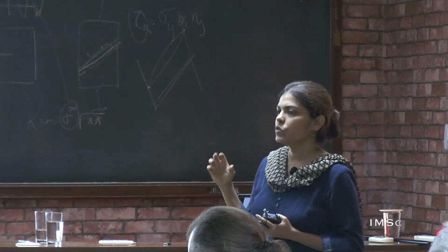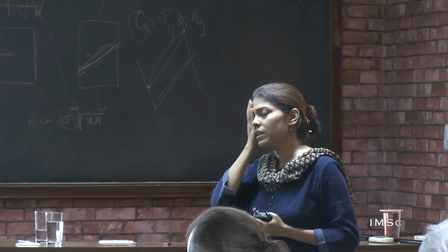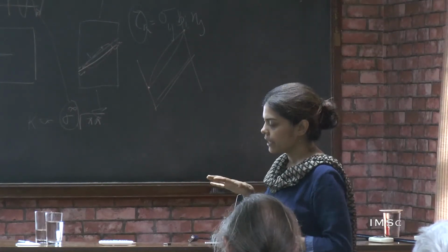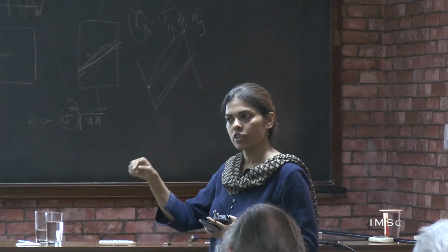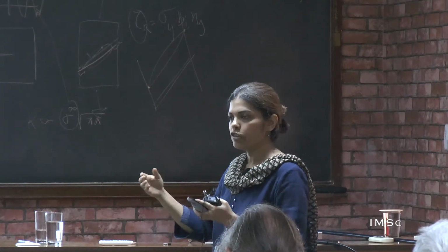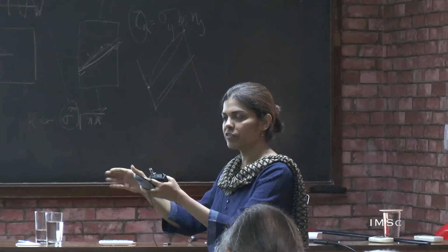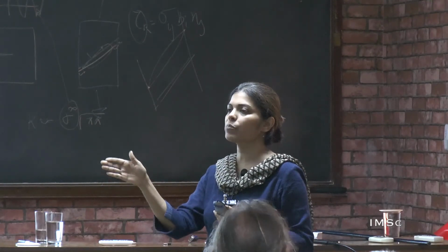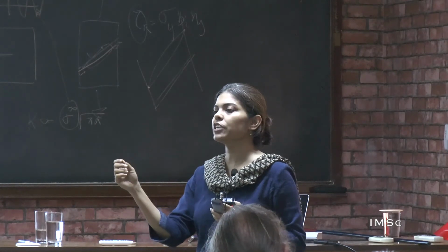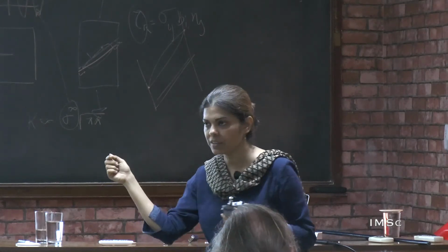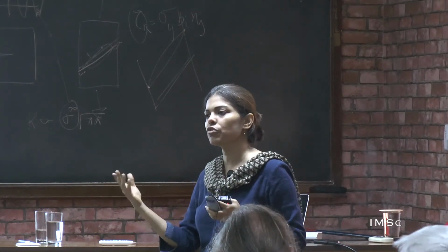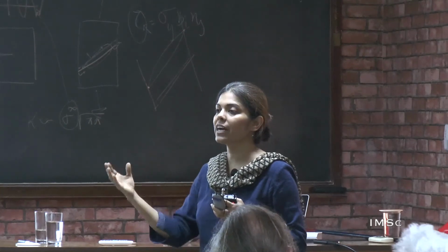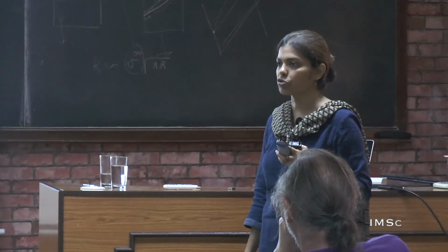The other evidence which motivated us in this direction was that if you see a fatigue crack, it actually progresses with its front in the middle. So there is some sort of tunneling happening. It kind of drags at the surface, and the center of the crack progresses forward. That is the location of highest triaxiality within the thickness direction. So that is also a manifestation of the fact that high triaxiality is conducive to fatigue damage growth.